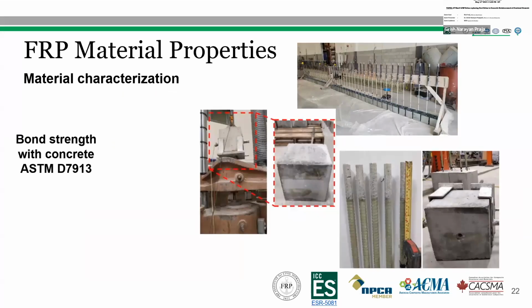Pull-out tests are performed to measure the bond strength between the reinforcing bar and the concrete. The GFRP bars were embedded in concrete blocks, and the concrete batch had a compressive strength of 35 megapascals. The pull-out test was conducted using a Baldwin testing machine as shown in this figure.